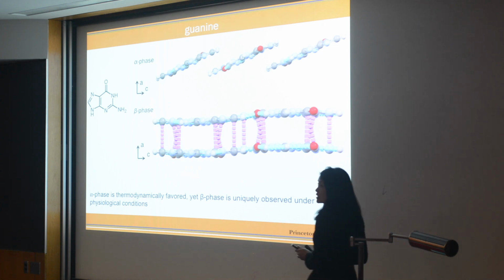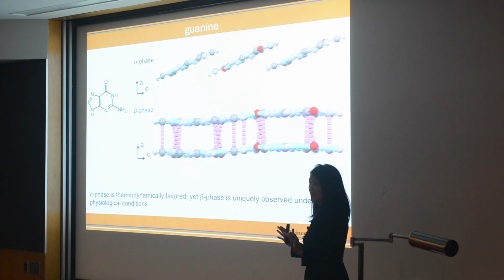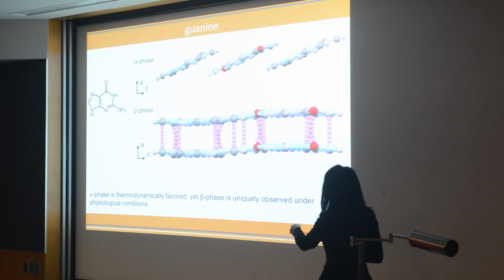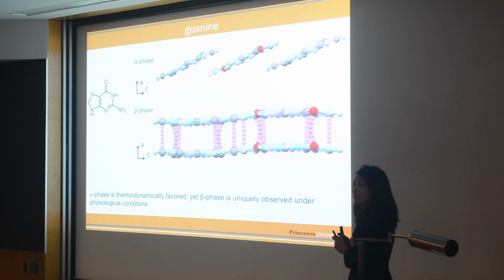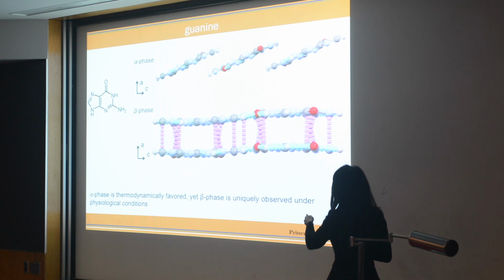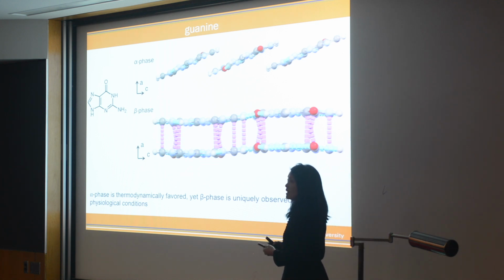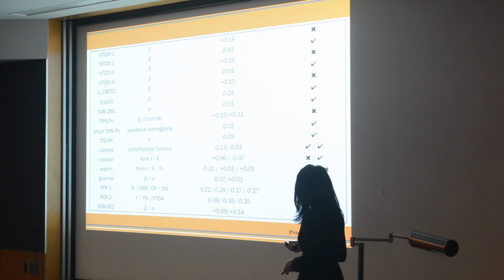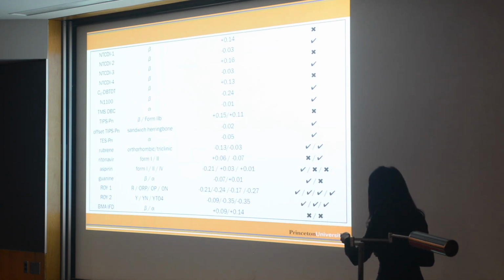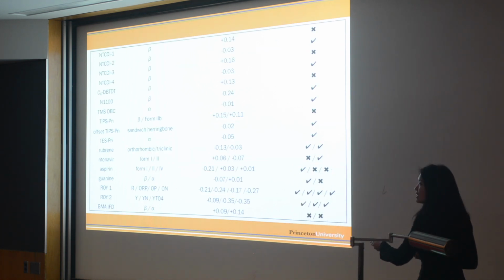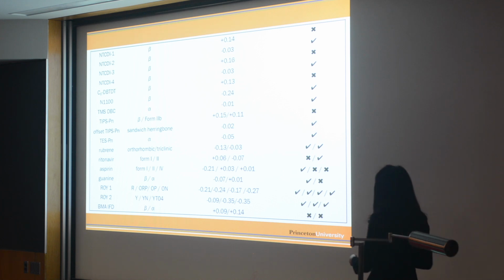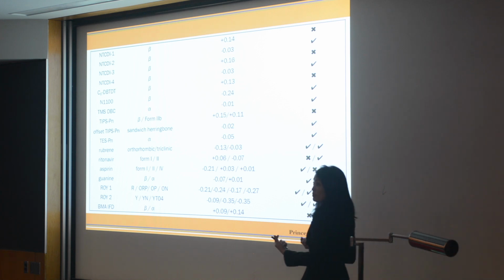And if you look at the crystal structure of alpha phase, there are no short interlayer contacts. The beta phase shows tons of interlayer short contacts. And again, we believe that these interlayer short contacts are what stabilizes this beta phase. So you can add those, and again, you can see the consistency. Whenever there's a negative number, the polymorph is stable. Whenever there's a positive number, the polymorph is not stable.